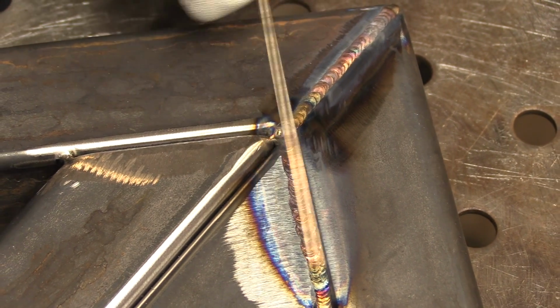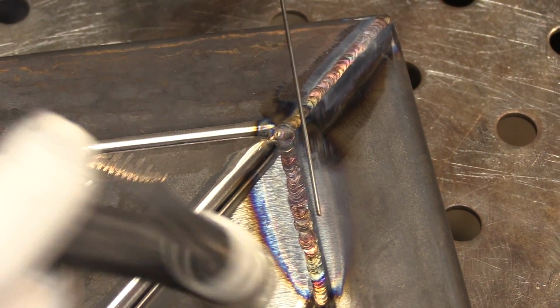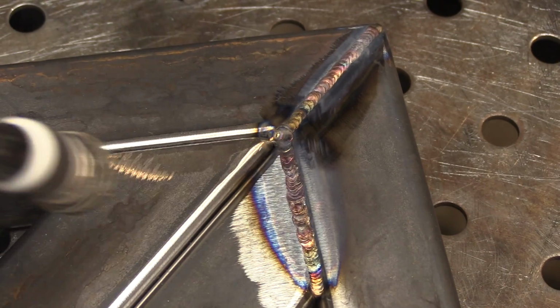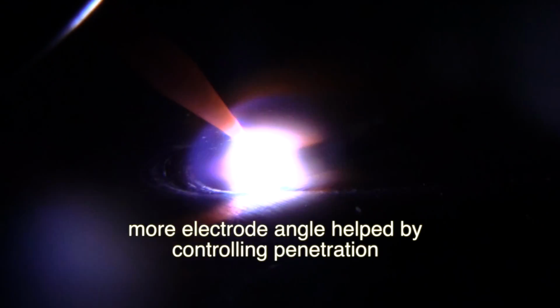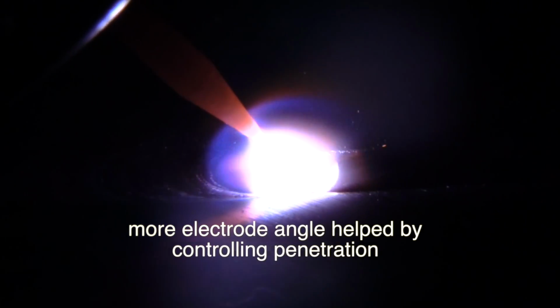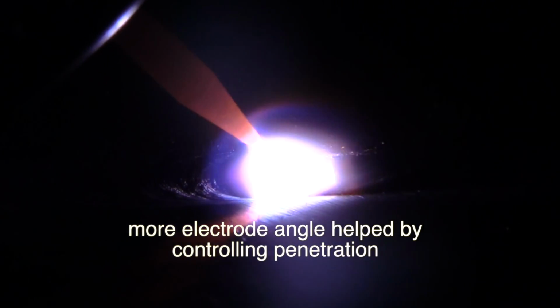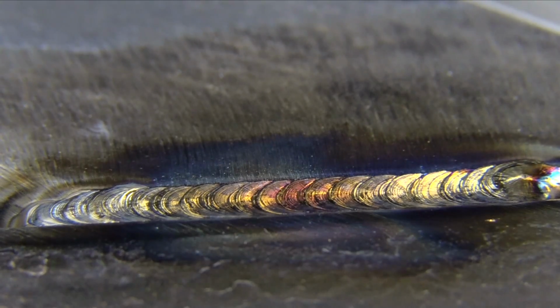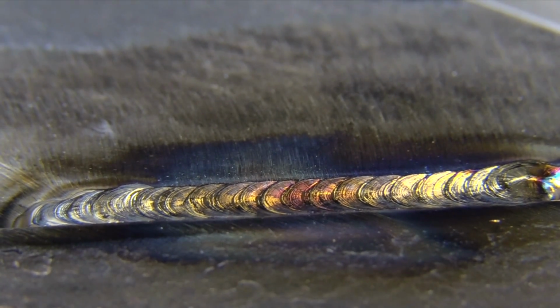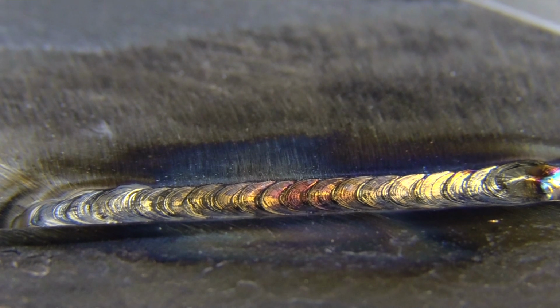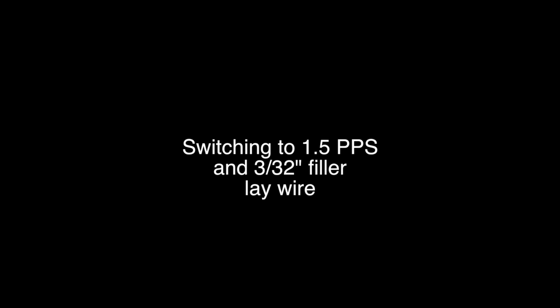So I think what I'll do is I'll try to modify my technique a little bit on the other side and just show you that real quick. I'm kind of using the other side for arc shots as I film this. What I did here is I just leaned the electrode way back. That usually winds up getting shallower penetration, and that's kind of what I want here. I mean, I want penetration. I want it to fuse. I don't want to be a cold weld, but I don't want to melt all the way through the backside and pull all those oxides in.